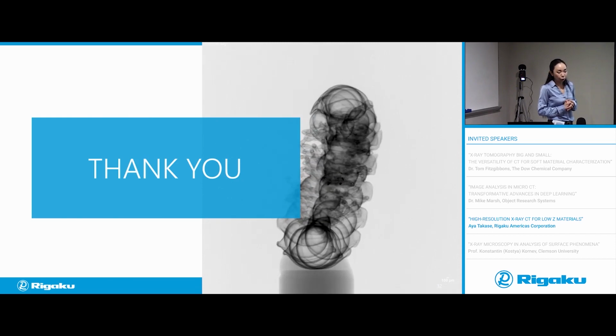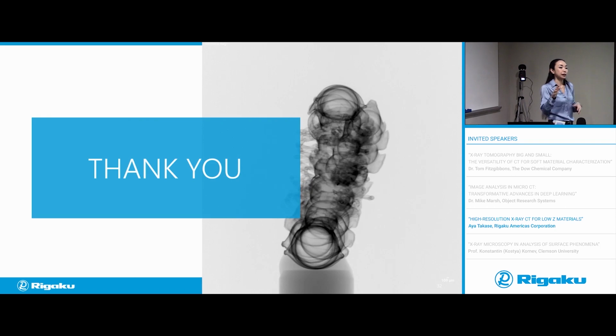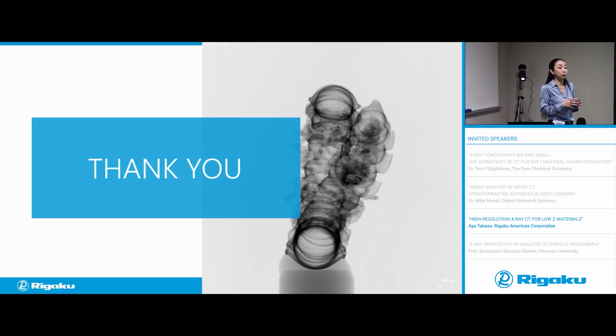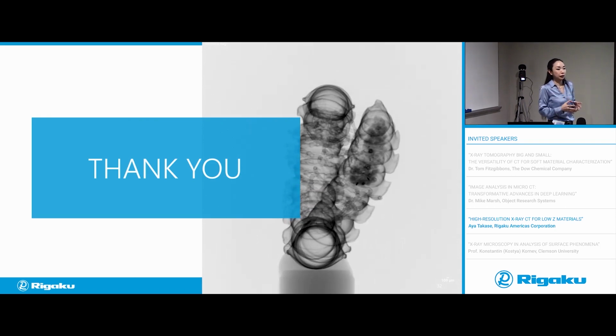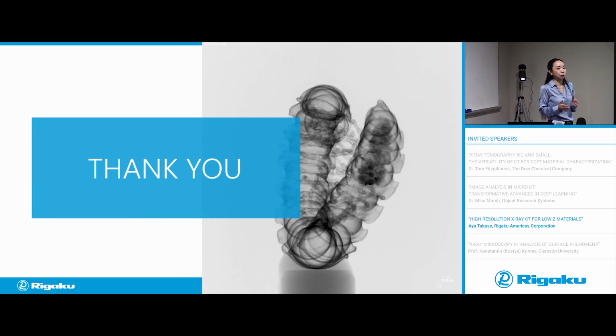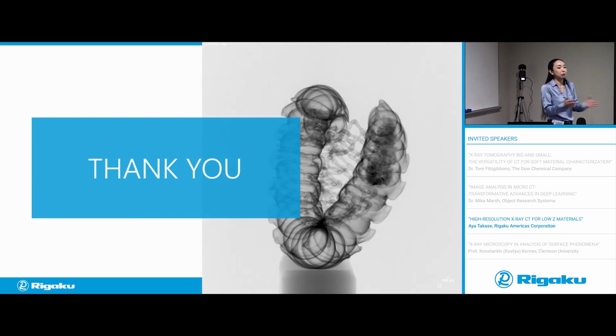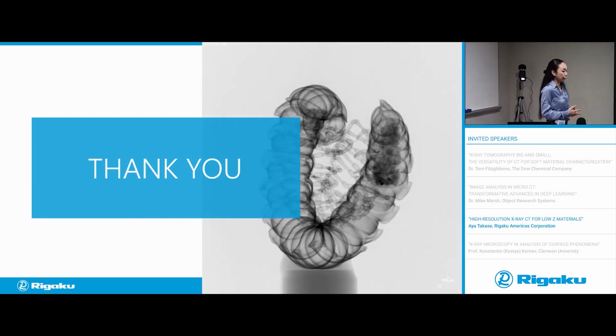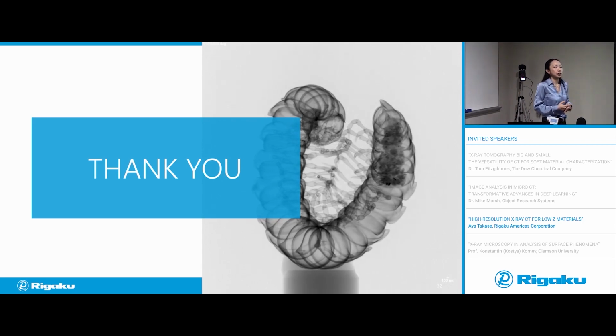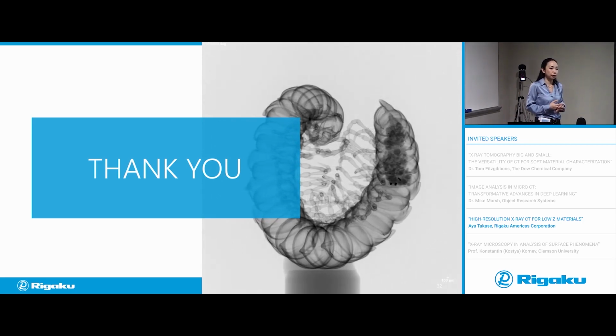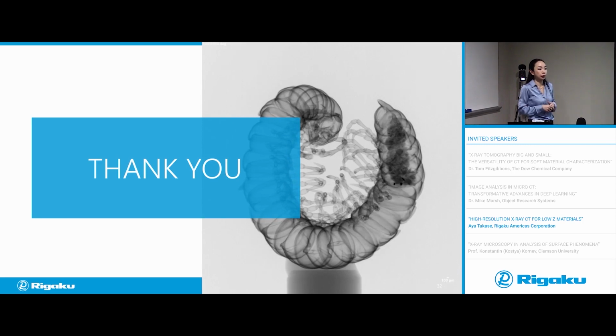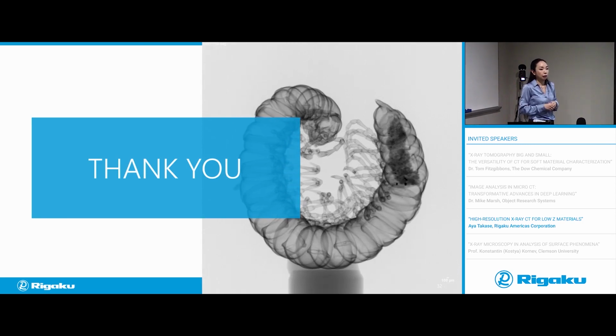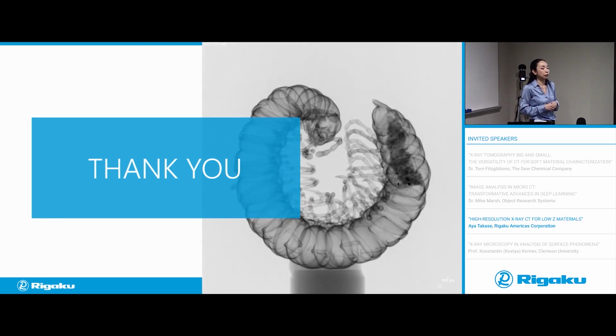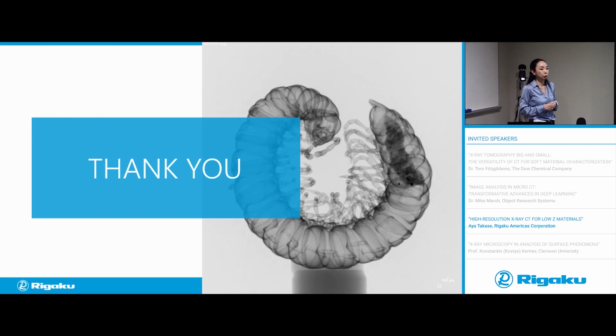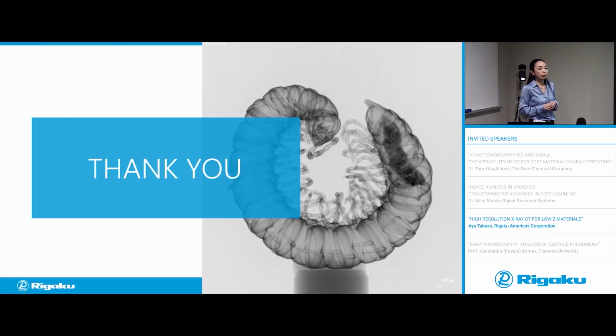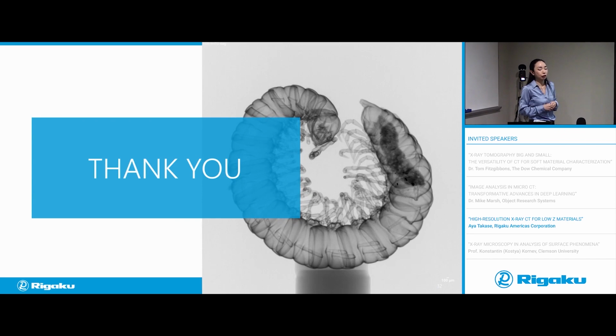Yeah, so in general, when you have a mixture of low density and high density samples together, that makes everything really difficult because you can't choose an X-ray energy that makes everybody happy, right? The common problem is that you see beam hardening artifacts or metal artifacts from the high density areas. There is a way to get rid of it to some extent with the reconstruction program, but never perfectly. So that can be challenging.